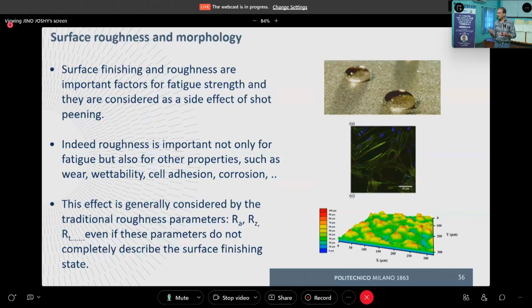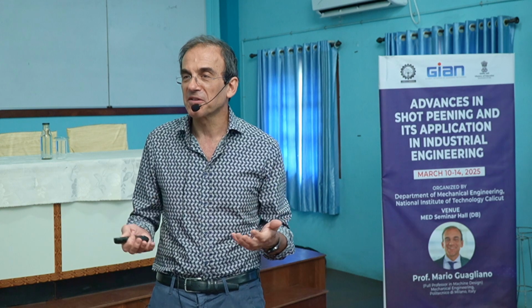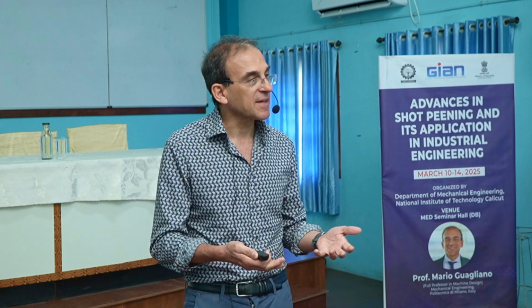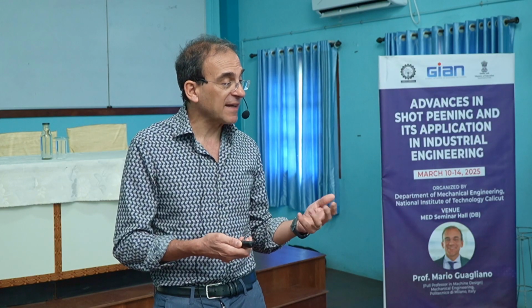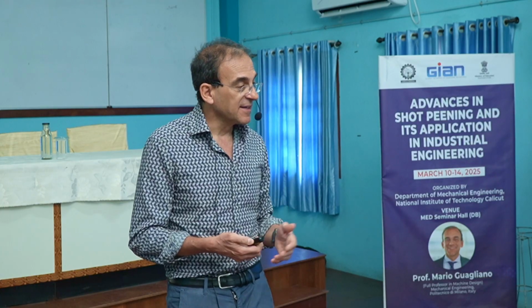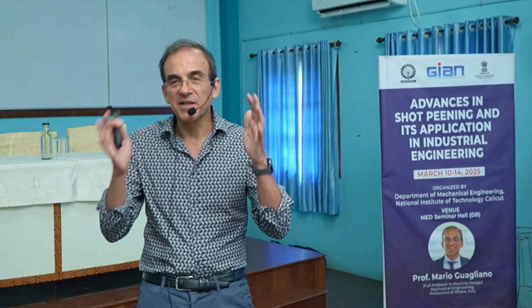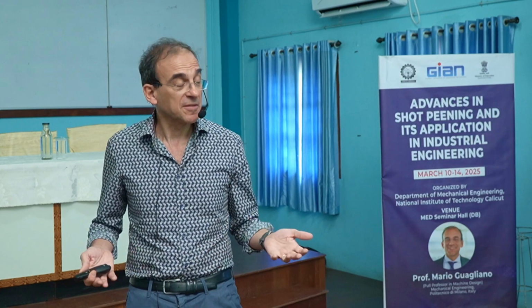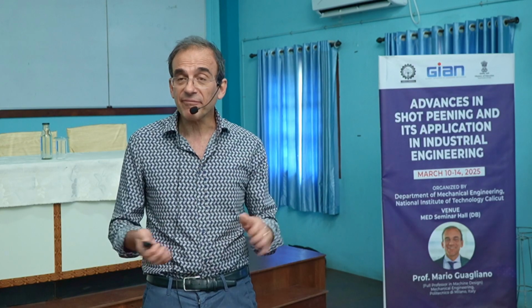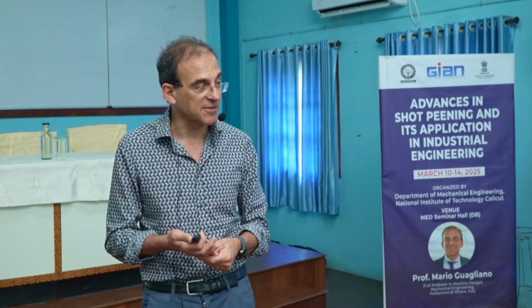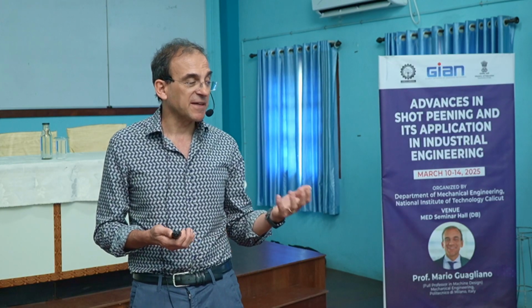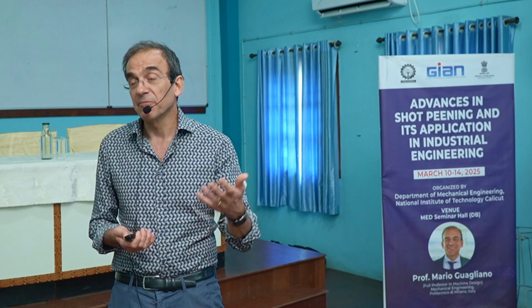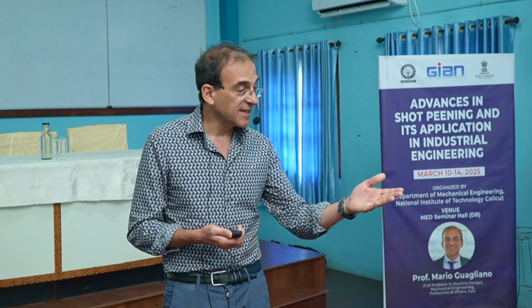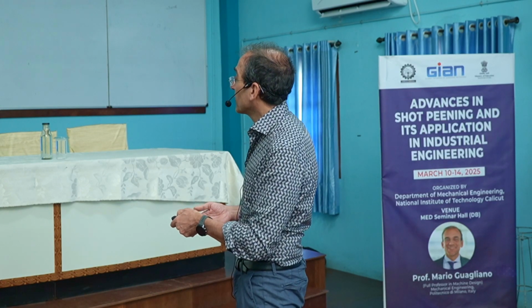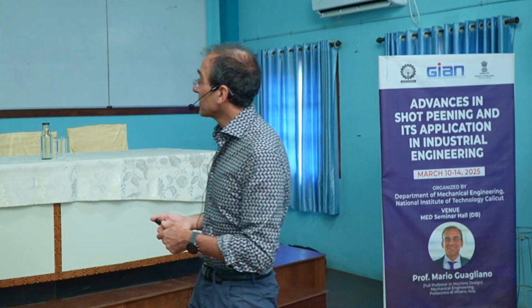Indeed, some cases, let's say, where roughness is not an unwanted side effect, where roughness can be used for adding some function to the surface. Indeed, we are used to thinking about shot peening just for fatigue, and this is understandable, of course, and this is still and will remain the main application of shot peening. But we can also consider some other applications where shot peening can give a contribution. Let's say here some of these functions can be seen: wettability, cell adhesion, corrosion. Okay, what is indeed wettability?